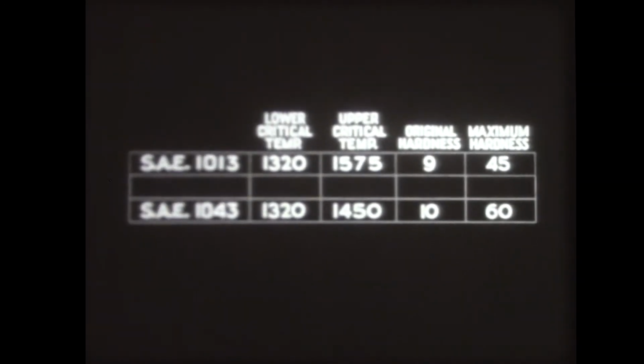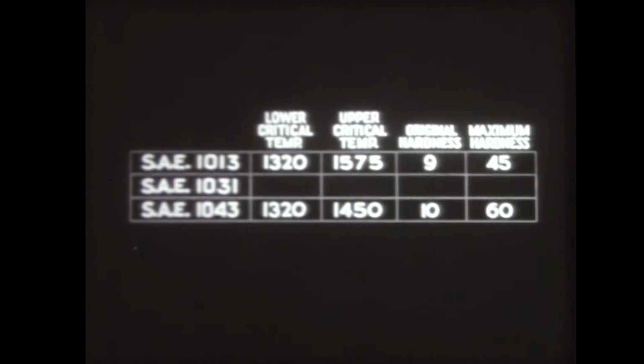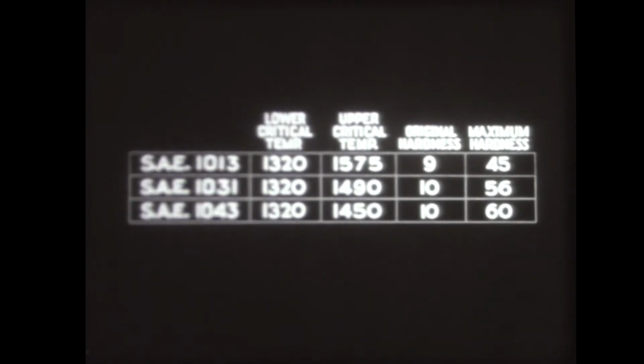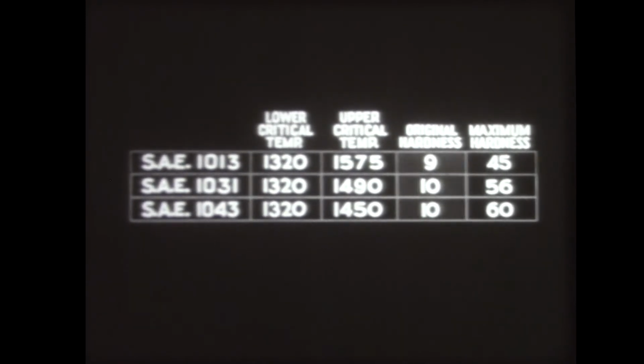And these are the comparative values. Lower critical temperature, 1,320 degrees. Upper critical temperature, 1,490 degrees. Original hardness, 10. Maximum hardness, 56. The first thing we can note from these data is that while before heat treatment, plain carbon steels vary only slightly in hardness, there is a wide range in their maximum hardness. And the higher the steel's carbon content, the higher is its maximum hardness.